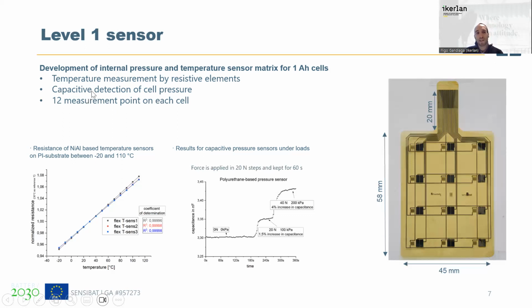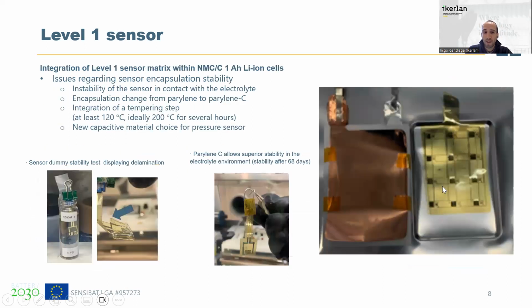And then for pressure, we are using capacitive detection elements. So if we apply a certain frequency, we can measure the capacitance of this element, and as it changes, we can obtain the pressure that we apply from the outside to the cell, or the cell is applying to the outside. In this case, for 1 ampere-hour cells, we have 12 measurement points, and you can see here how we implemented it in the cell. So it's between the electrode and the pouch bag.